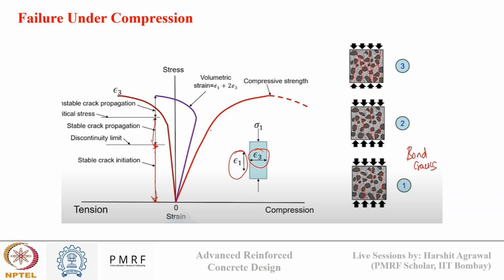So this figure just summarizes this entire compression failure of concrete. Initially, we can see in the first image the cracks are initiating in the ITZ near different aggregate and cement paste regions. The aggregate is in dark color, and in between, the light gray color represents the cement paste. You can see several red lines marked, which show the cracks initiating at the ITZ. Now, as the loading increases, these cracks connect and propagate to form bigger cracks, connecting between two ITZs. And finally, when they connect to give rise to a failure plane, this results in a compression failure, which you can see in the last image, how these cracks are completely connecting and propagating throughout the cross section of concrete.